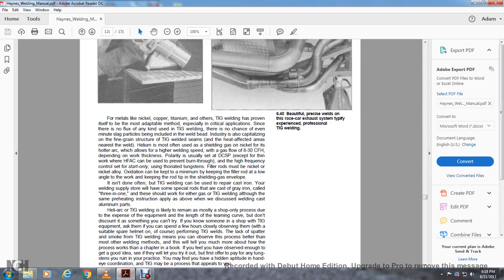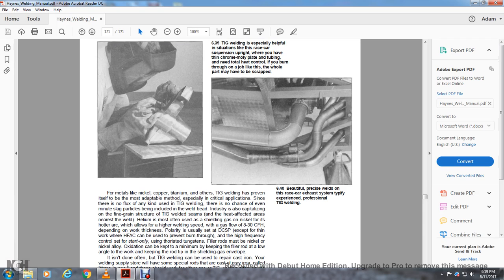For metals like nickel, copper, titanium and others, TIG welding has proven to be the most adaptable method, especially for critical applications. There is no flux in any kind of TIG welding, so there is no chance that even a minute slag particle will be included in the weld bead. Industry also capitalizes on the finer grain structure of TIG welding, which keeps the heat-affected area near the weld small. Helium is most often used as the shielding gas on nickel because it gives a hotter arc, which allows higher welding speed, with gas flowing at 30 cubic feet an hour.